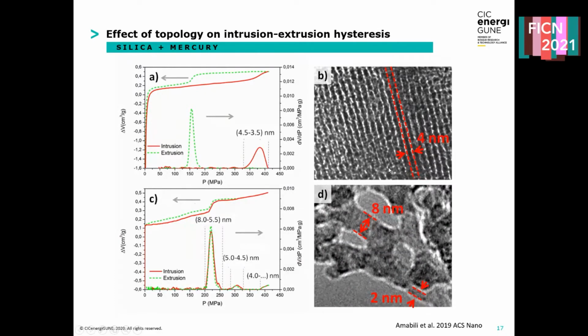And it seems that this statement is true not only for water. So here is an example of intrusion of mercury into mesoporous silica. Not that we are interested in using mercury for practical application, but just to generalize this observation, we explored the intrusion of mercury into highly ordered channels of MCM41 silica, and we saw quite pronounced hysteresis of intrusion-extrusion.